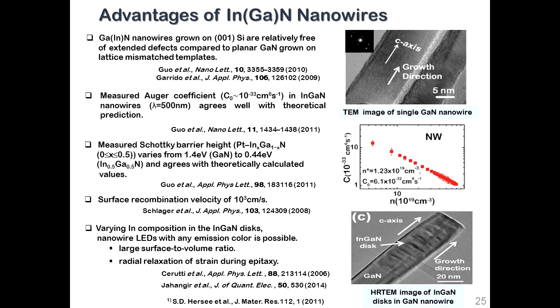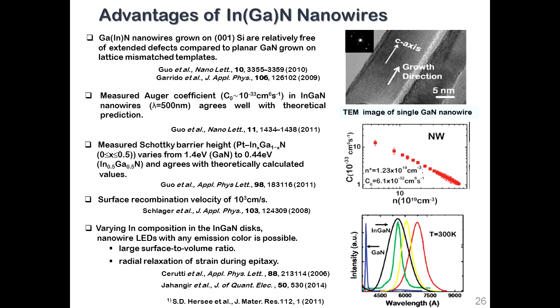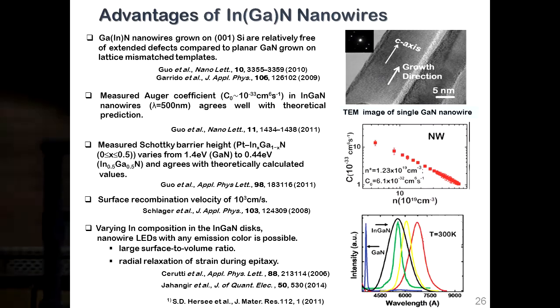We've done, and other groups have done, a lot of work. We've measured Auger coefficients, and for the first time, these coefficients agree with theoretical calculations. We've measured Schottky barrier heights. The surface recombination velocity is 2 orders of magnitude smaller than that of gallium arsenide. And of course, you can put these so-called quantum disks, these heterojunctions of indium gallium nitride in a gallium nitride nanowire, and you'll see why we do that. We can vary the composition of these disks, and you can get any color from violet to red. So they are very versatile.